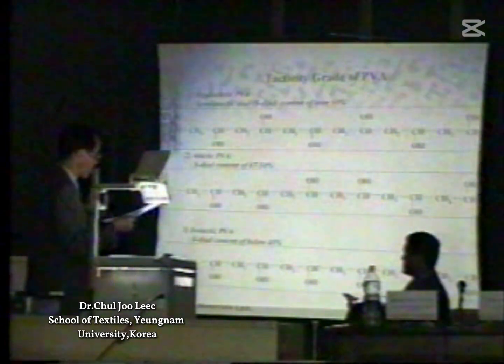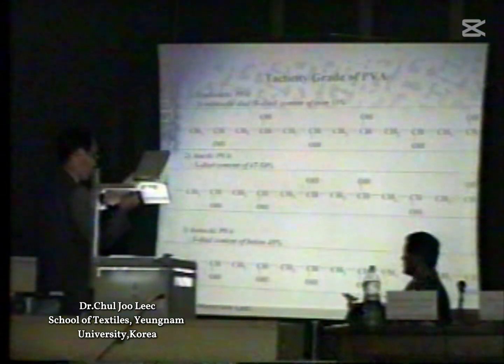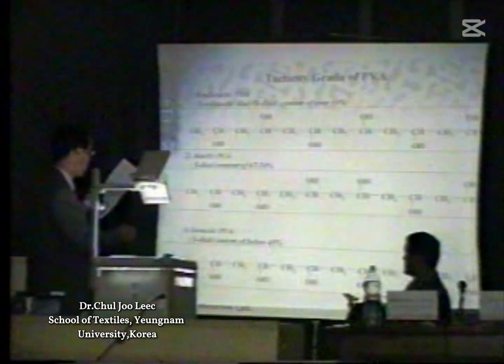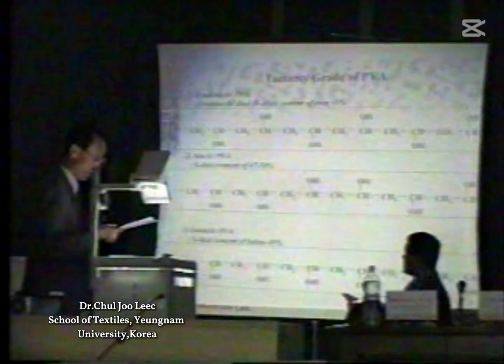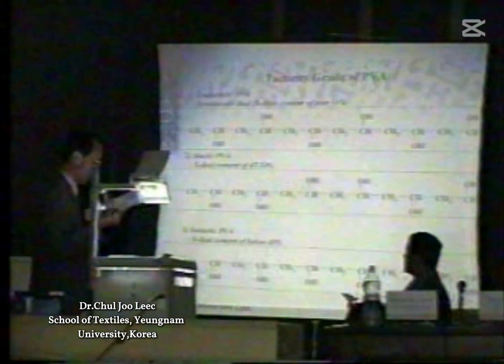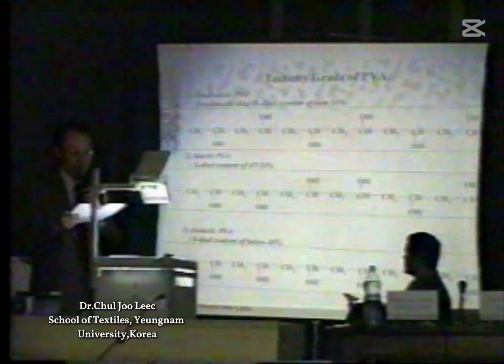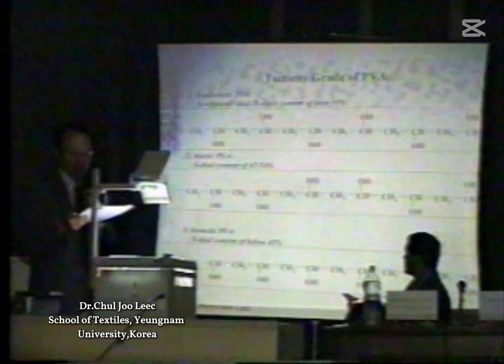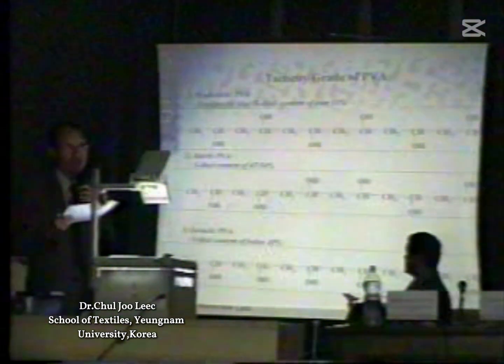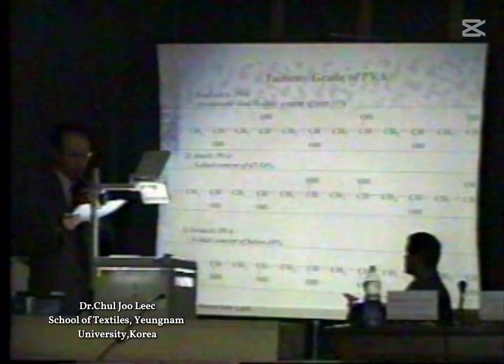While a syndiotactic diad content of 47% to 54% is called atactic. This one has totally irregular stereoregularity. And below 45% is called isotactic PVA. As you know, syndiotactic PVA has better properties than atactic PVA due to ease of hydrogen bonding between the neighboring chains. For this reason, many attempts are made to increase the syndiotacticity of polyvinyl alcohol.